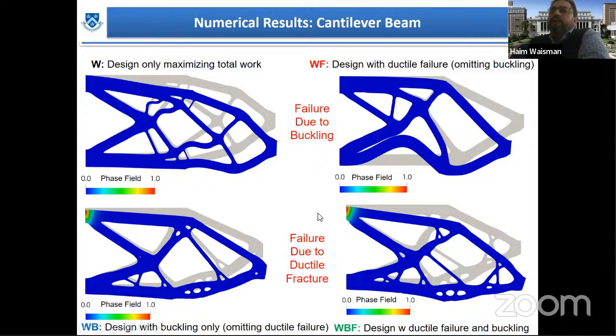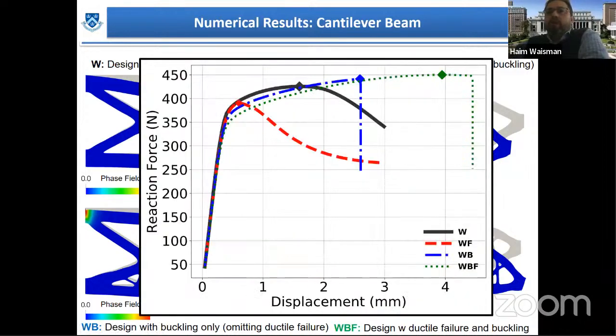So which one is actually better? We have to look at the force displacement curves. And what do we see? We see the following four different designs. The best design is noted by the green point, and this includes both the buckling and failure constraint. What's interesting is that we can increase the peak load or strength of the material by about 15% and almost 900% increase in ductility, which is very important for applications such as energy dissipation, where you want to increase ductility as much as possible.